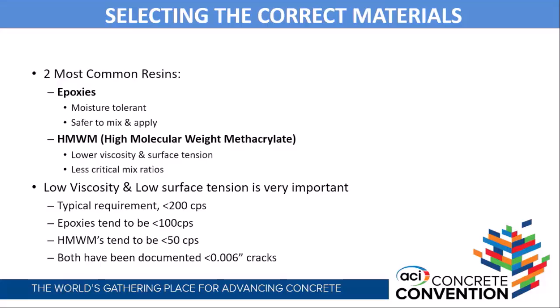Epoxies are a little bit more moisture tolerant than methacrylates, and they're safer to mix and apply than methacrylates. Whereas methacrylates typically have lower viscosities and lower surface tension, so you get better penetration. So that question about getting into smaller cracks, methacrylates are going to do a much better job, especially with just gravity pressure. However, you have to be careful. There are some hazards when you talk about mixing methacrylates.